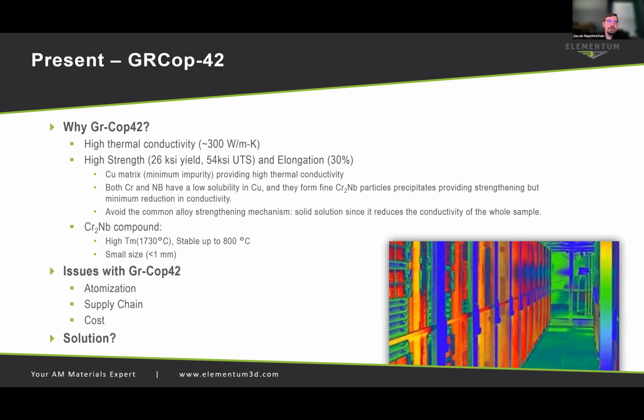What we're doing with GRCOP 42 today, I don't want to go too far into it because I think there's going to be other people that really get into this, but I want to talk about some of the issues with GRCOP 42, which tend to be in the atomization and supply chain and the cost of that material. It's very difficult to make GRCOP 42. It contains these chromium niobium compounds, which have a much higher melting temperature than the copper itself. So you have to go to a very high superheat in the copper. What that means is you have to go to a temperature well above the melting temperature of copper to melt those precipitates to get a good distribution of those elements so that when you do atomize, you have a nice consistent powder. Well, the problem with that is then you start to dissolve the crucible.